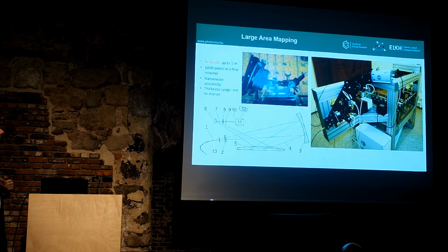And the last example is the mapping of large surfaces. It can be adjusted. So we have a point-like light source. You illuminate a large surface. You can illuminate even a 1 meter sized surface. You can have maybe 1,000 measure points, and each point can be measured simultaneously, because the reflected light comes to a CCD detector. So each point of the detector corresponds to 1 point of the surface on the sample. And in each point of the detector, you have this sine square change of the signal. So the polarization state of the light can be determined for each pixel of the detector simultaneously. So we have 1,000 points very quickly, and you can measure a large surface within a very short time.